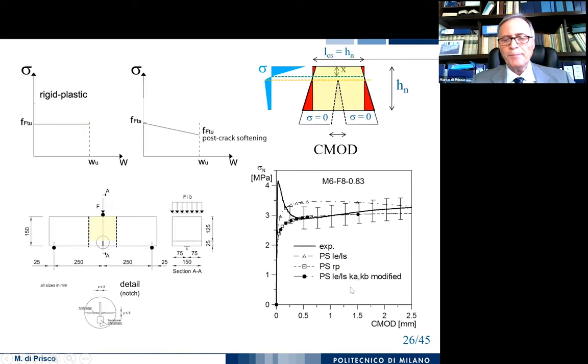But we can see also in bending, if we adopt the assumptions that I already explained, that you cannot cover the cracked zone, but you can cover the residual zone, which corresponds to what we are interested in, because we are interested in the behavior after the cracking.